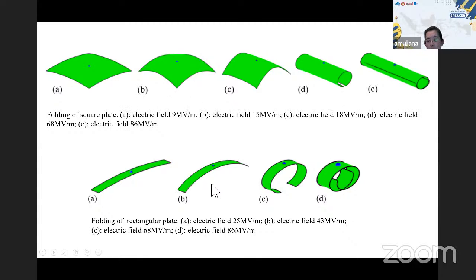Of course, the response would really depend on the geometry of this component. When we look at just a square geometry, in the beginning it tends to create a dome shape, because the minute you activate the electric field, there will be stretching uniformly across this plate, right? However, these plates need to achieve their stable state. So at some point there is a snap, and it goes to the cylindrical state, because this is actually the stable state, which requires a small amount of energy.